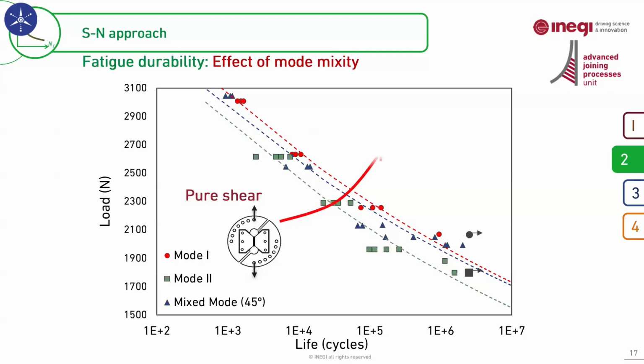Our research group has conducted several direct method projects as well, in collaboration with various industries and companies. And I'm going to share with you some of these results. One of the most important parameters that must be analyzed experimentally when using the indirect method is the effect of loading mode. So we have to analyze the effect of loading mode by changing the loading angle from pure mode 1 to pure mode 2.